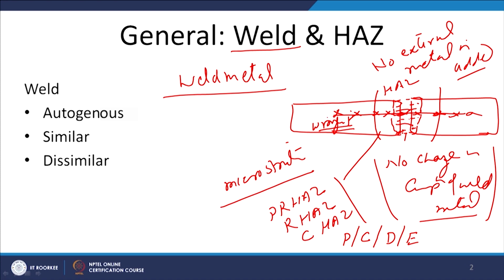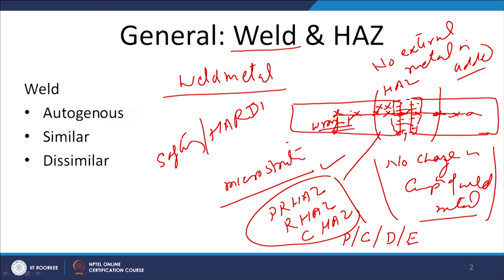So, despite having the same composition, since the melting has taken place, the subsequent solidification and the heat affected zone have experienced the weld thermal cycle, so it will also have different microstructural changes. So, despite no change in the chemical composition of the weld metal, whenever a base metal is welded by the fusion welding process, there is always a structural variation, and depending upon the characteristics of the metal, there can be softening or there can be hardening,